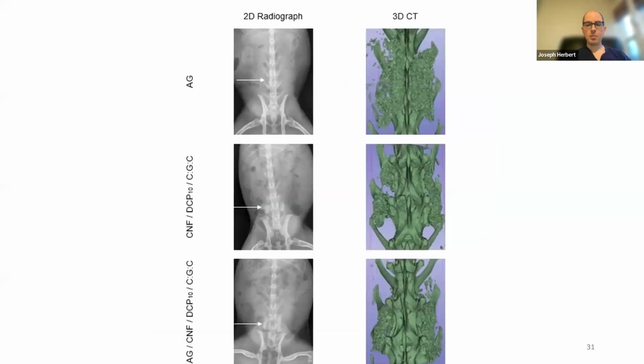So these are examples of the X-rays on the left side, and then the post-necropsy CT scans. And really, I've found that the X-rays are in some ways easier to interpret than the CT scans, because these 3D reformatted CT scans, to me, are a little bit difficult to interpret. But this would be an example of a rabbit with very minimal fusion. We see a little bit of maybe bony formation. This is just allograft. That's what AG stands for. On the CT scan, you still have the material in place. It's possible that this rabbit might go on to fuse at some point.